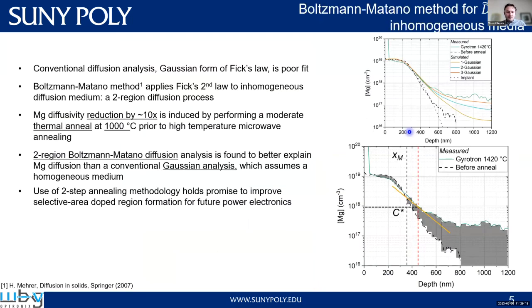I then analyzed the diffusion behavior with a conventional Gaussian diffusion analysis, as well as with a much less common Boltzmann-Matano approach. The Boltzmann-Matano approach, as I showed in the talk in Berlin, explains the diffusion of magnesium better than the more conventional analysis. I also find that magnesium redistribution can be suppressed by performing two anneals successively, and show that this method holds really a lot of promise for improving future power electronic device performance.